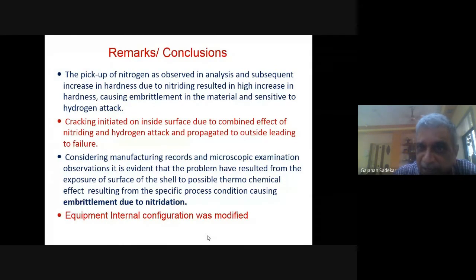Considering the manufacturing records, though I have not shown you all the manufacturing records we collected, we actually analyzed them to see what the original hardness was at various places and what the composition was, all that I talked about during the discussion of the methodology. We did that and we found that everything was normal at that time. And then we drew the conclusion that this has happened because of the thermochemical effect resulting from the specific process condition causing embrittlement due to nitridation.